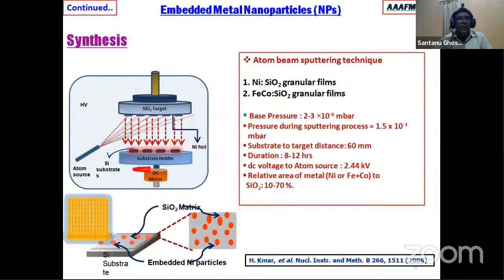We grow nanoparticles embedded in silica matrix by a process called atom beam sputtering technique, where an atom source is used, and this sputters silica as well as the metal pieces glued to the silica target. Eventually, after sputtering, they fall on the substrate, which rests on a substrate holder that also rotates, so it forms a uniform film. In this particular study, I will discuss two films. One is nickel SiO2 granular films, and another is iron cobalt SiO2 granular films. And these are the deposition conditions which we use during the deposition process.